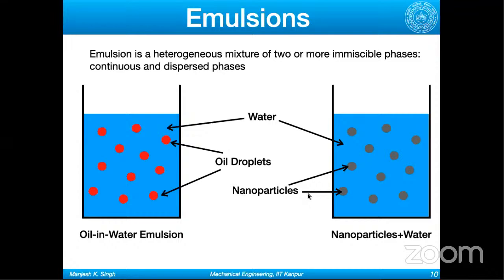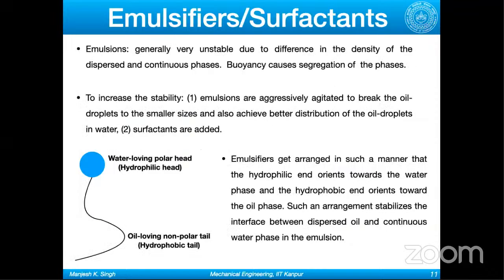So then, emulsifiers or surfactants, why do we need them? Generally emulsions are very unstable due to the difference in density of the dispersed and continuous phases. So you have water and oil, or nanoparticles and water, with a density difference. If you use large particles, they will just sediment at the bottom. If you use very small particles, then because of the high surface area to volume ratio and van der Waals attractions, they will come together and form clusters. So you will not have a well dispersed emulsion.